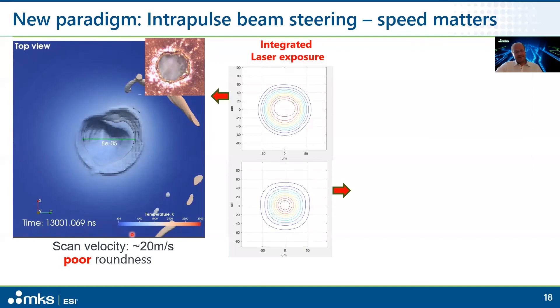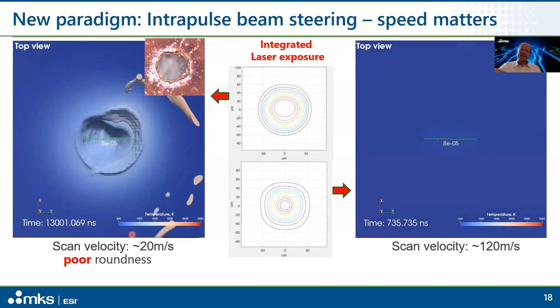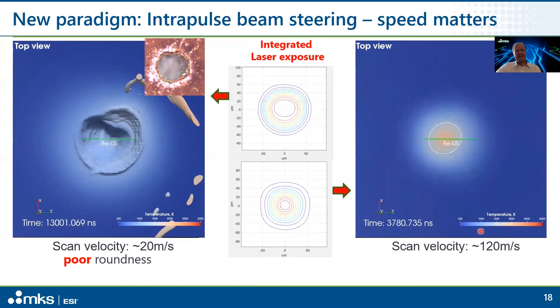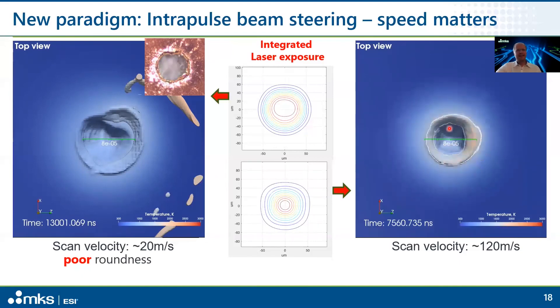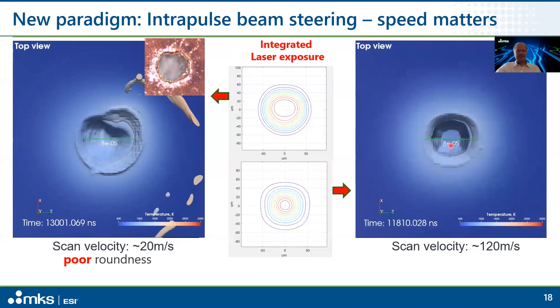We can model whatever we want, so we ask: what happens when we move much faster — at 120 meters per second? Now you can see that we move sufficiently fast that the thermal diffusion is sufficiently symmetric, so we get ejection not following the optical spot but naturally happening at the center of the average motion of our optical spot. With that, we get a nice round via, and that is borne out by experiment. Yes, you can still reach these speeds with the acousto-optic deflector.